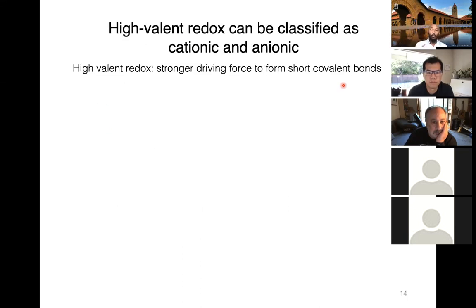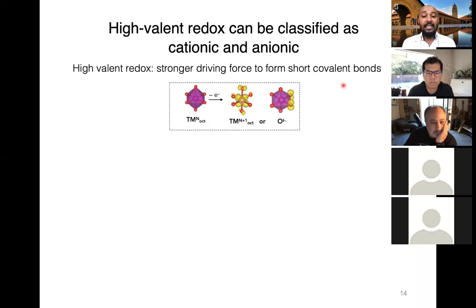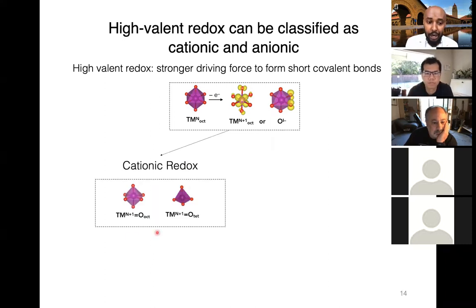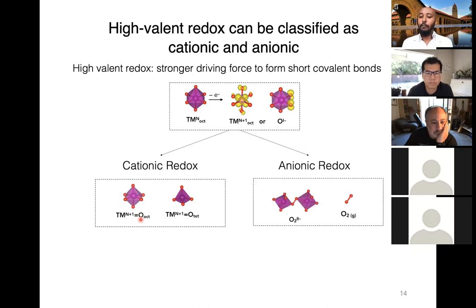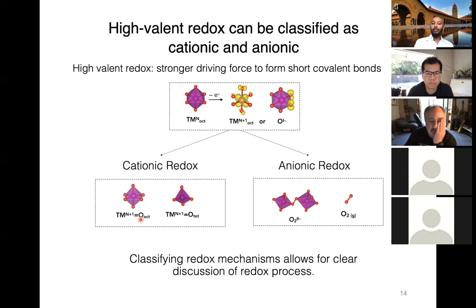Like I mentioned, one of the definitions of high-valent redox is that there's a stronger drive to form a short covalent bond. Based on this definition, we can actually classify high-valent redox into two different mechanisms. The first one is if this short covalent bond is formed between a metal, like a transition metal, and oxygen, shown over here, we call it a cationic redox because the metal is a cation. If this short covalent bond is formed between anions, in this case, oxygen anions, in the form of peroxide or oxygen gas, we call this anionic redox. And such classification of the high-valent redox will allow us to understand the exact mechanism of high-valent redox in the material, thereby using the understanding to be able to engineer materials with higher capacity and lower cost.